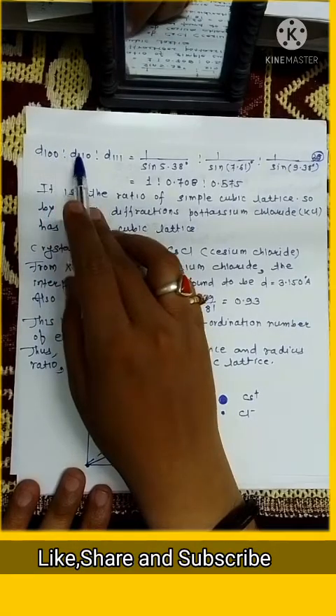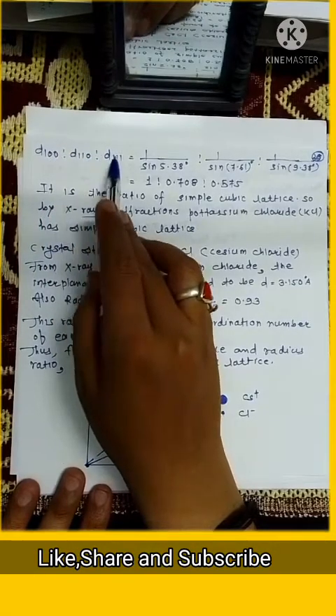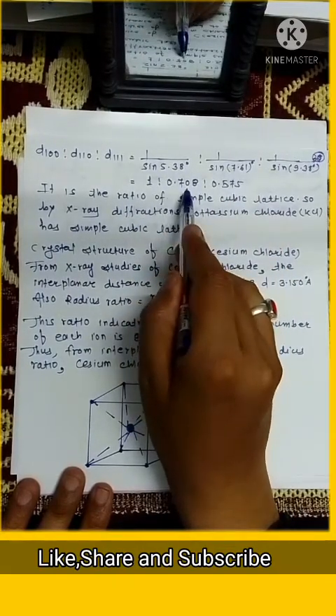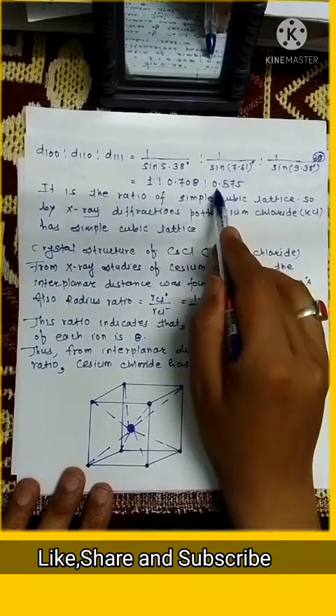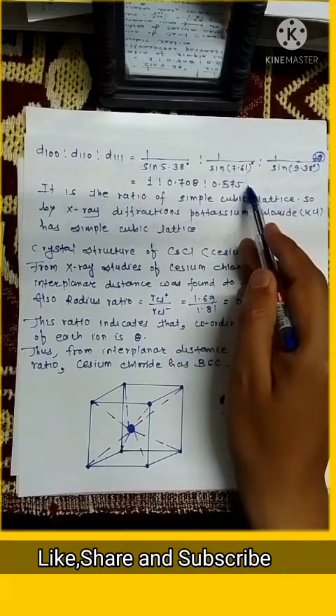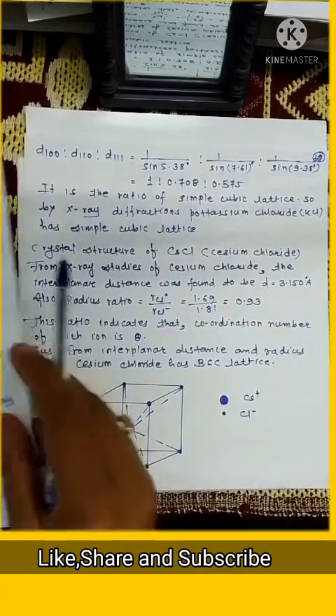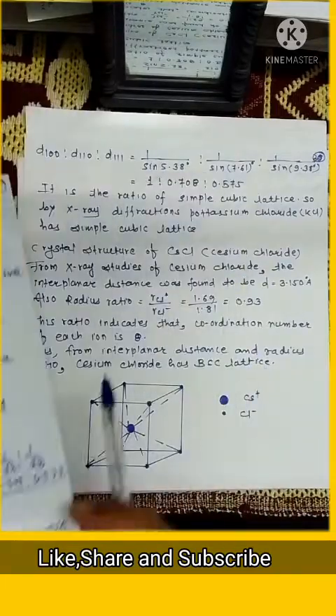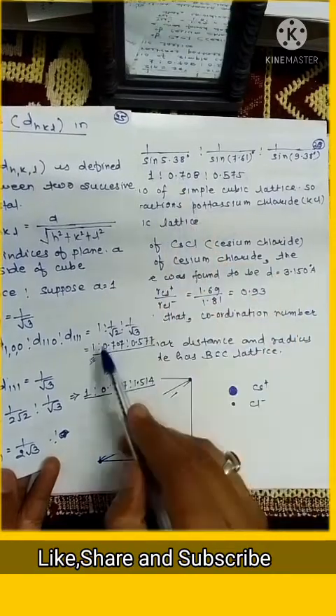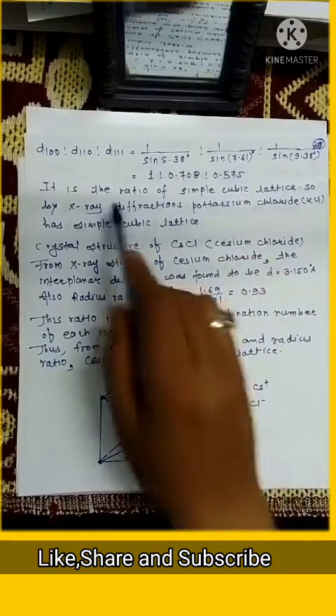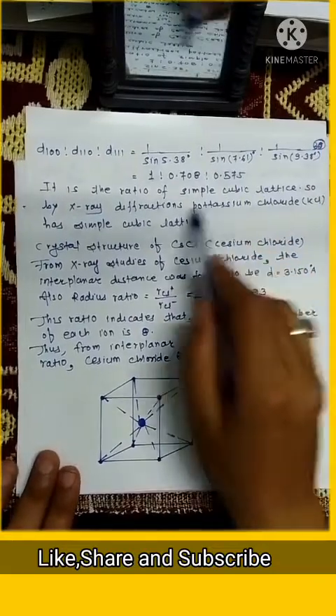This is equal to 1 : 0.708 : 0.575. Now we compare this experimental ratio with our theoretical ratio. So from here we clearly see that your KCl is of simple cubic lattice type of structure. So it is the ratio of simple cubic lattice.